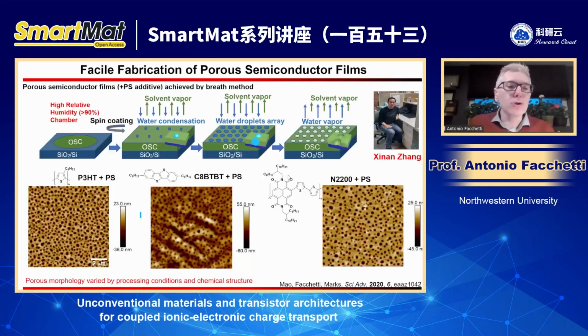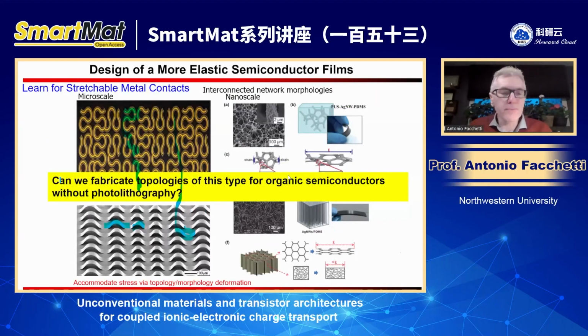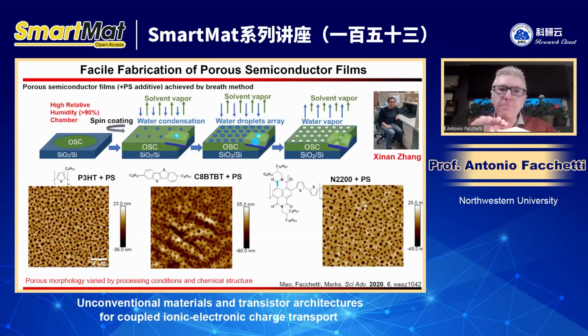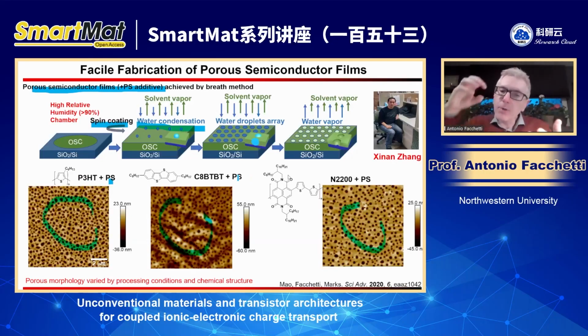So one way we have been able to embed porosity, this is not like this, but it's very similar to a certain extent. These are AFM images of three organic materials, where we have fabricated pores by breath figure. The breath figure is a technique where you can spin coat a polymer or a molecule solution. You have your semiconductor plus a little bit of polystyrene, spun in a very high relative humidity atmosphere. Water condenses on the film before the solvent completely evaporates. So water droplets create holes in your film. What you see here, the black area is where the water was present, and around it, the lighter area is where the semiconductor plus a little bit of polystyrene is present. This is a very easy way to have holes in your semiconductor film without using photolithography. So it's a sort of photolithography done very, very easily.